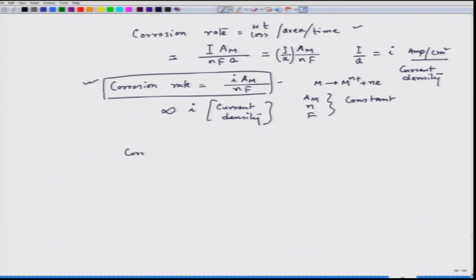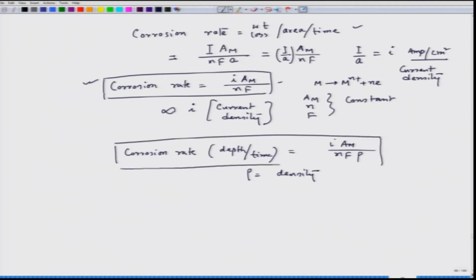So, the corrosion rate in the form of depth per unit time, we can put it as I A M by n F rho, where rho is basically density. So, we get another expression like this, which is equivalent to weight loss per area per time per density.